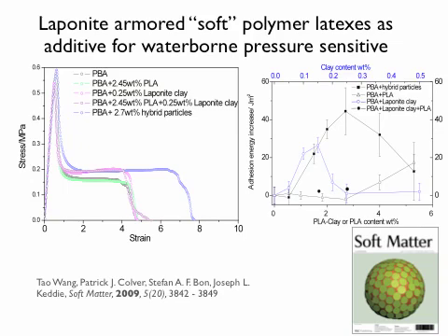Then you make a blend of these two things. So I've got a polybutyl acrylate latex, my clay particles, and my soft latex dispersed through each other. And then I do my experiment, and what you'll see is exactly the same as the reinforcement with the clay, but no big difference. Then you use your hybrid particles. So now you have your armored latex. Do the same experiment at 2.7 weight% of this. This is a fraction, right? Massive difference. So the area under this curve is a measure for the adhesion energy.